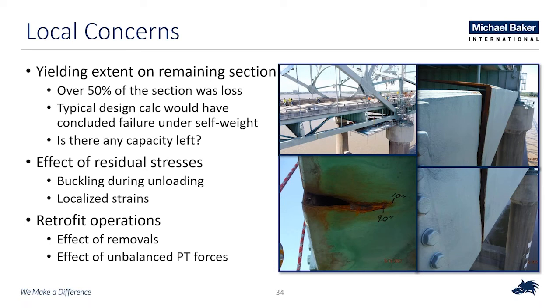The second concern is that we wanted to evaluate the effect of residual stresses. When there is a large amount of plastic deformation in a plate, localized residual strains might form, and you can have some form of buckling during the unloading. We wanted to make sure that we didn't have any strange situation where we have any sort of local instability.